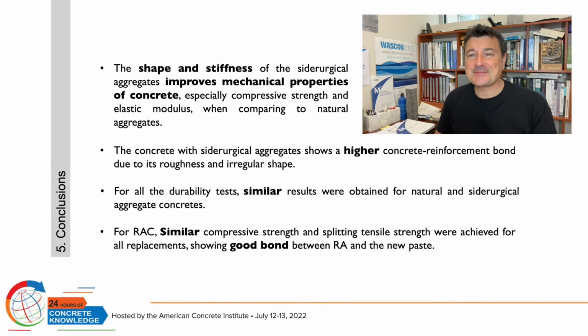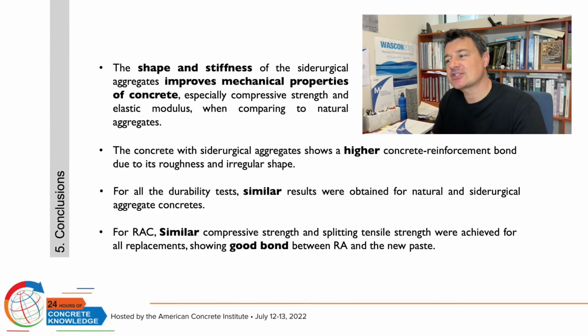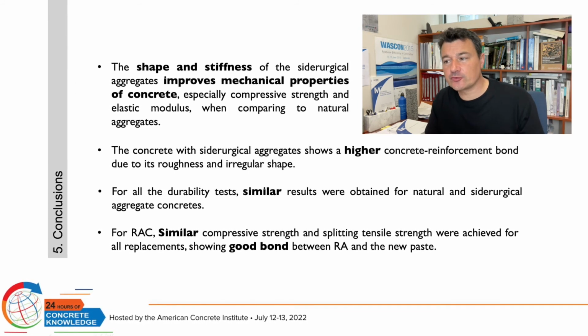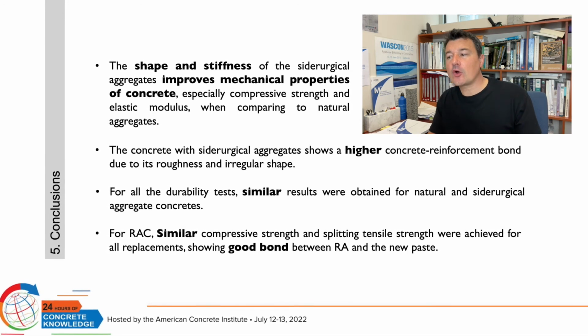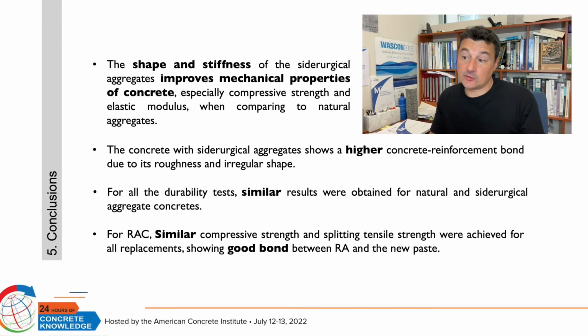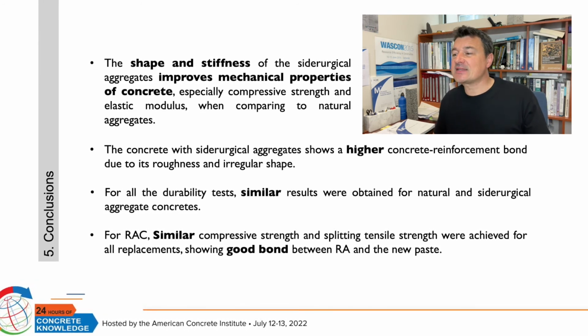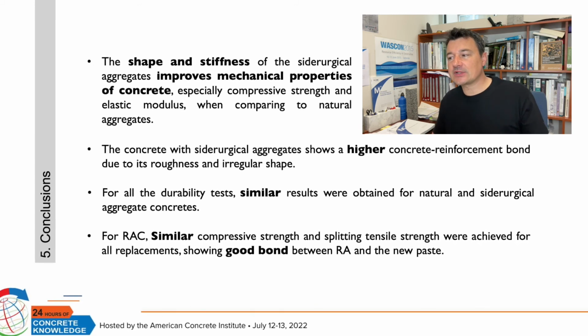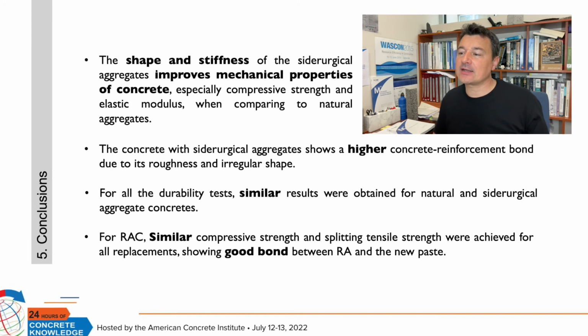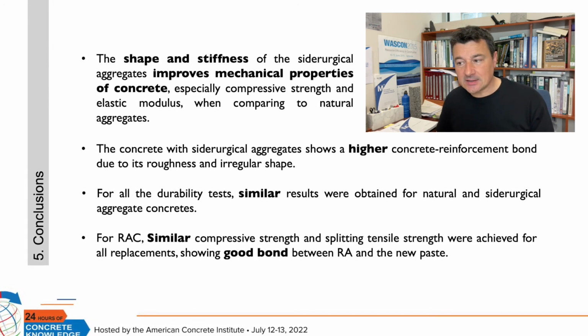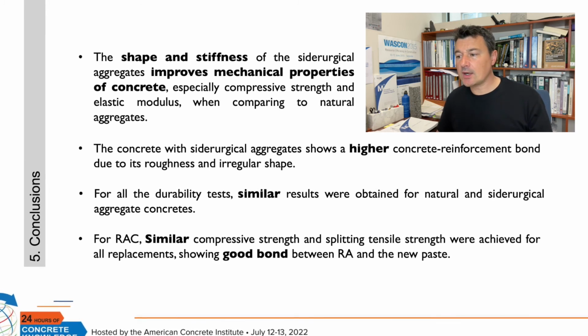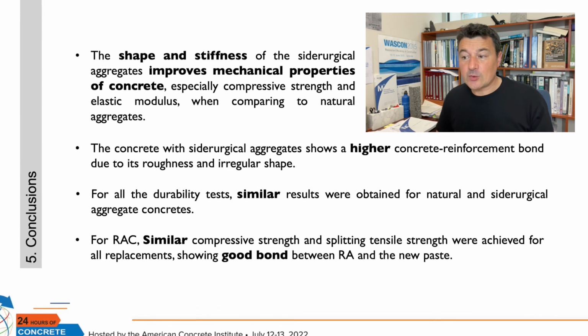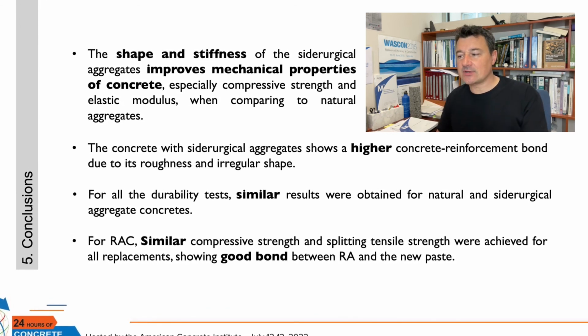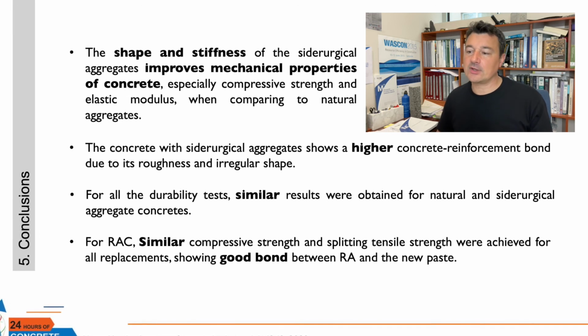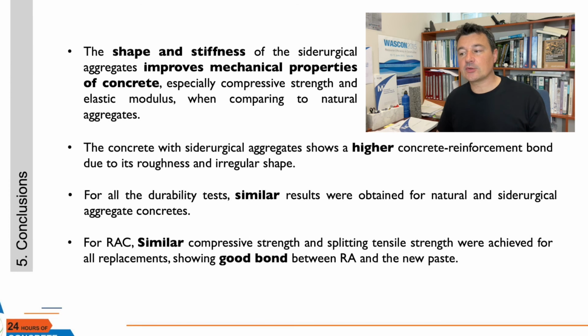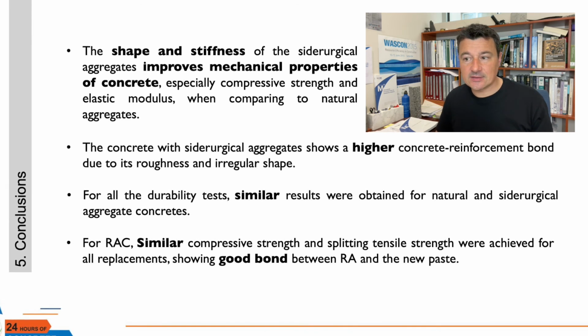So to finish, let me read the conclusions. The shape and stiffness of the siderurgical aggregates improve mechanical properties of concrete, especially compressive strength and elastic modulus, when compared to natural aggregates. The concrete with siderurgical aggregates shows a higher concrete-reinforcement bond due to its roughness and irregular shape. For all the durability tests, similar results were obtained for natural and siderurgical aggregates. For recycled aggregate concrete, similar compressive strength and splitting tensile strength were achieved for all replacements, showing good bond between recycled aggregates and the new paste.